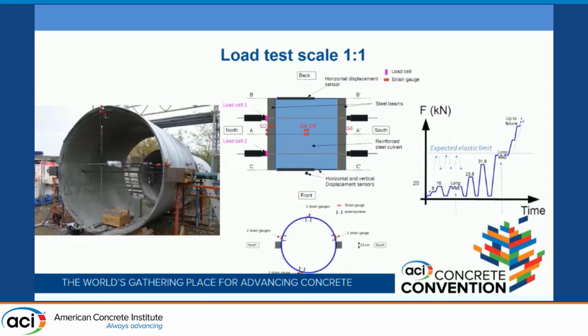A loading test at scale 1 has been performed. The metal culvert was first reinforced and then loaded with the help of two transverse beams, transferring the forces of the bar put in traction by jack. The wall was instrumented to follow the loadings, the deformation, and the stress values. Different loading and unloading cycles were applied. After determination of the elastic limit, the load was increased until failure of the test body.